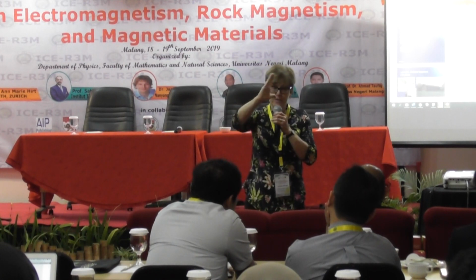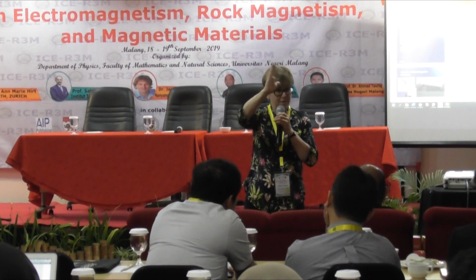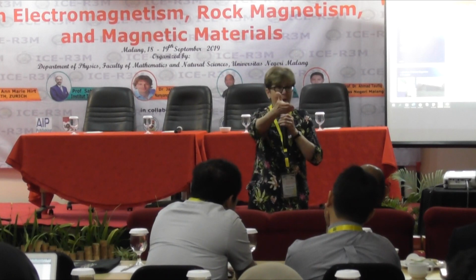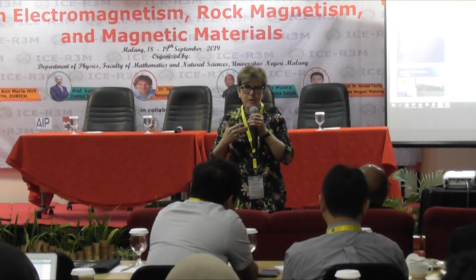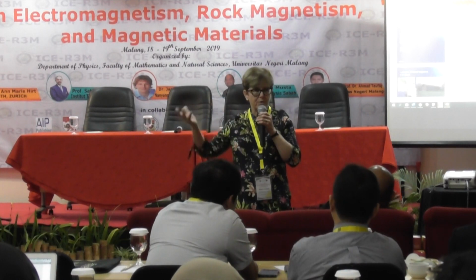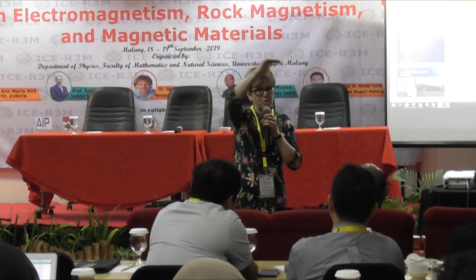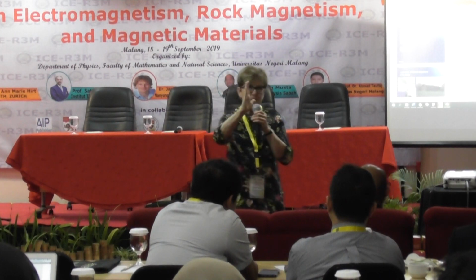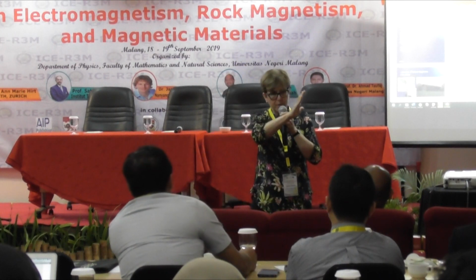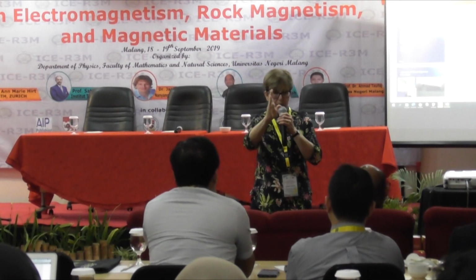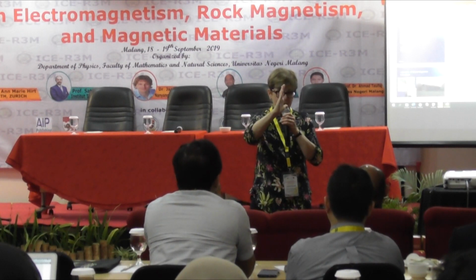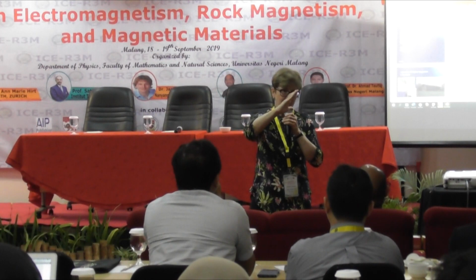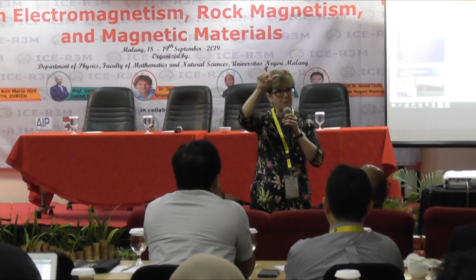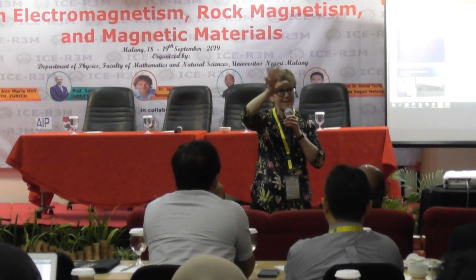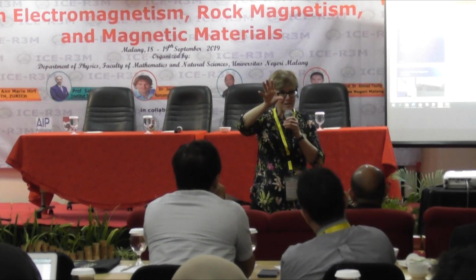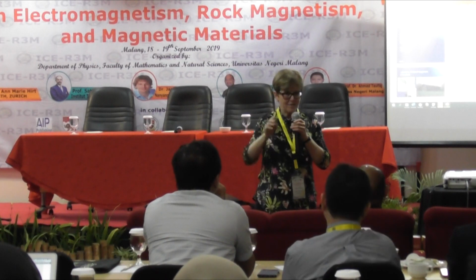If you have a high surface area, your spins don't line up, you have these uncoupled spins, and so it will look paramagnetic. But what we notice is that as long as they are certainly 5 nanometers or larger, you will see a very steep slope and you will see saturation. What we find is if you're close to the boundary between single domain and superparamagnetic, the slope is very high, and as it gets smaller and smaller, the slope becomes less, partly because of those uncoupled spins at the surface. You can't saturate that magnetization. Does that answer your question?